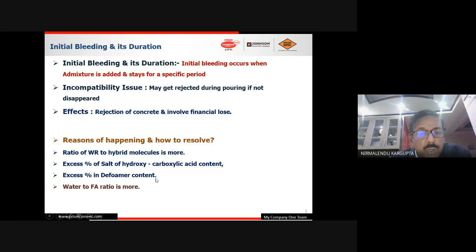एक्सेस परसेंटेज ऑफ डिफोमर कंटेंट आपने डाल दिया, उतना जरूरत नहीं था, आपने 0.1% ऑफ द फॉर्मुलेशन दे दिया. जरूरत ही नहीं था उतना. 0.07 डालने से ही होता, 0.05 डालने से ही होता. क्योंकि उसमें थोड़ा जो हल्का सा एयर चाहिए, that will not kill the strength that is required for the good rheology, वो आपने पूरा भगा दिया एयर को. So these aspects have to be considered.